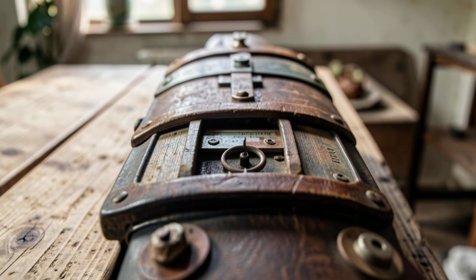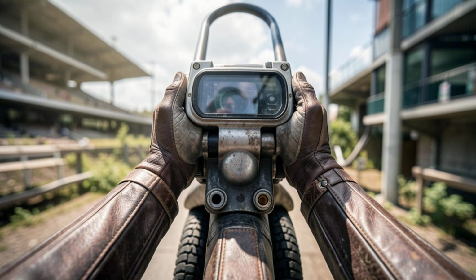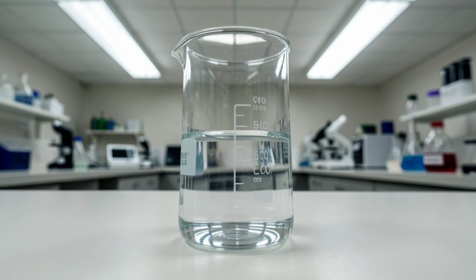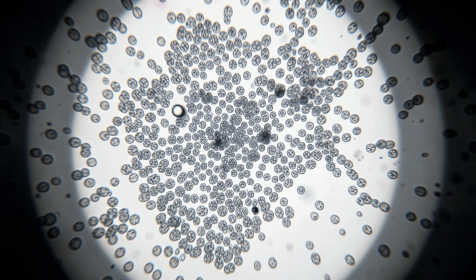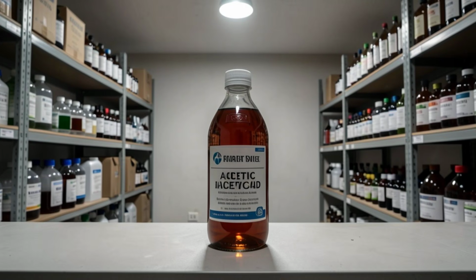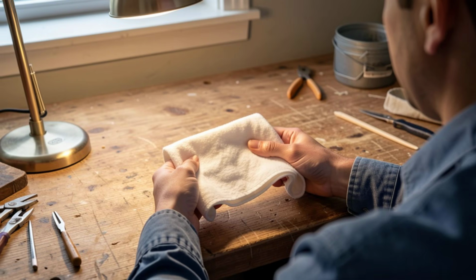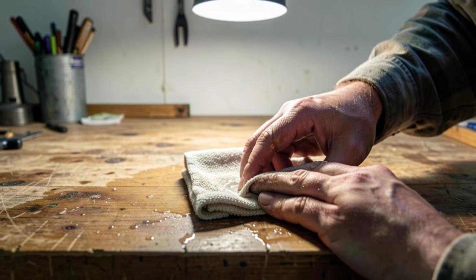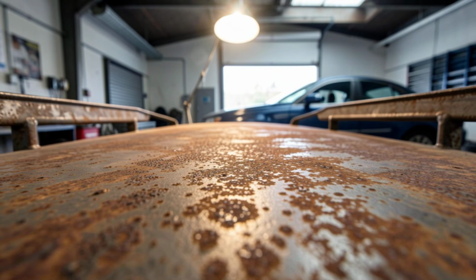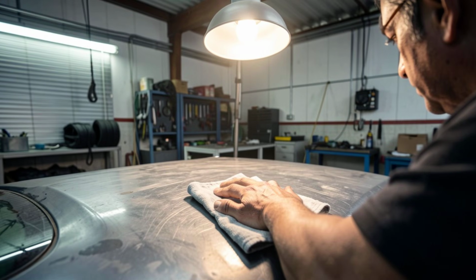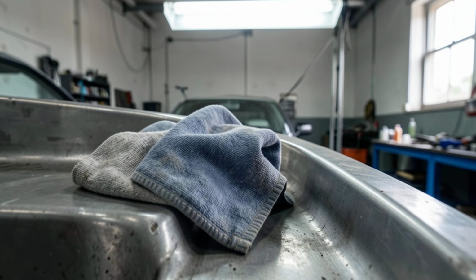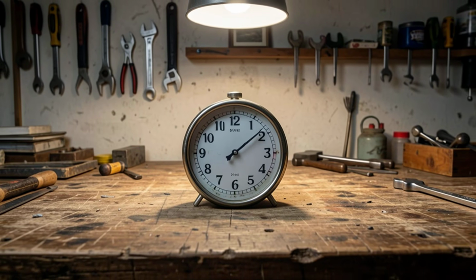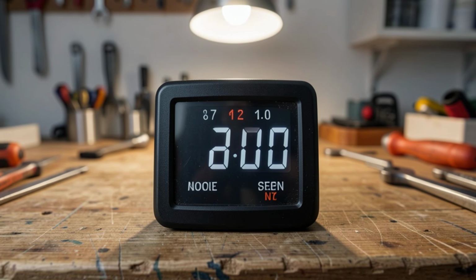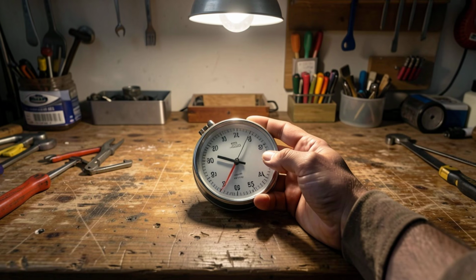Here is the exact protocol. Mix 1 cup of plain white vinegar with 2 tablespoons of coarse salt. Stir until the salt is completely dissolved in the vinegar. You want full dissolution so that the chloride ions are evenly distributed throughout the acetic acid solution at maximum concentration. Take a clean cotton cloth or a stack of paper towels and saturate it completely in the solution. You want the fabric wet enough that it will maintain contact with the rusted area without drying out during the treatment period. Lay the saturated cloth directly over the rusted metal surface and press it firmly into the contours of the panel so you have continuous wet contact with the entire affected area.